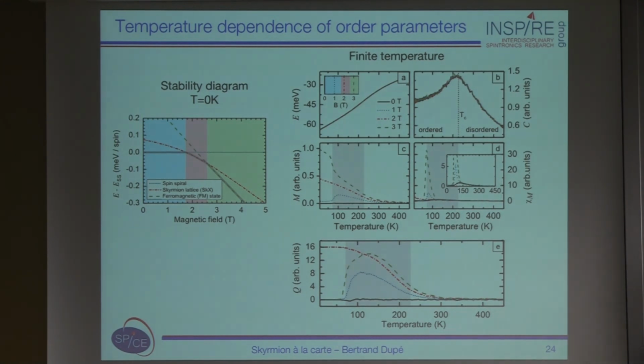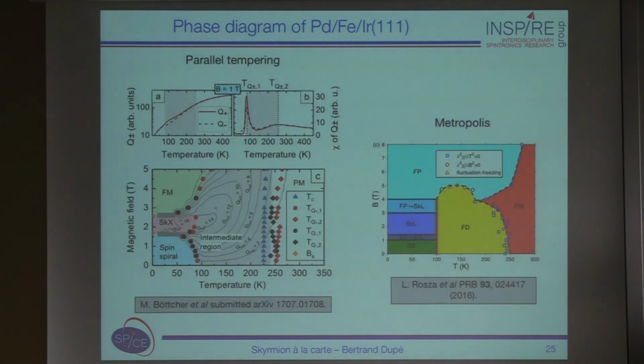However, since I told you the topological charge does not mean anything, we can have whatever skyrmion and anti-skyrmion in the system. So actually, it is much better to look at the skyrmion and anti-skyrmion pair creation, which we call Q plus Q minus. And this is what is shown here on the left. So this is the Q plus Q minus as a function of temperature. And here you have the susceptibility of the Q plus Q minus quantity, so the susceptibility of the creation of skyrmion and anti-skyrmion.